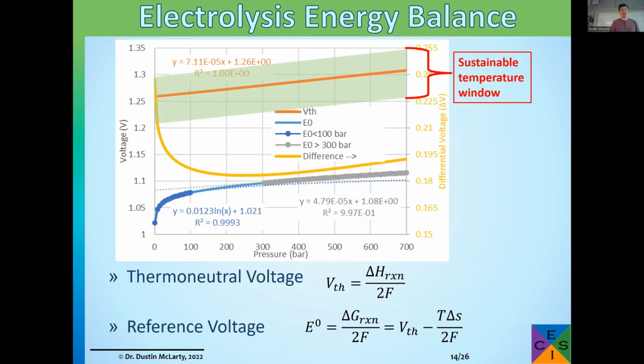On the bottom, and in the blue line, I'm showing the reference voltage. And this is the electrochemical potential of the cell. If you were at 50-50 hydrogen and steam, you're going to be right on this line. If you have extra humidity, your open circuit voltage is going to be below that line. If you have very dry hydrogen, your open circuit voltage is going to be above this line.